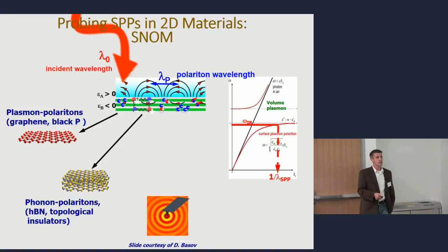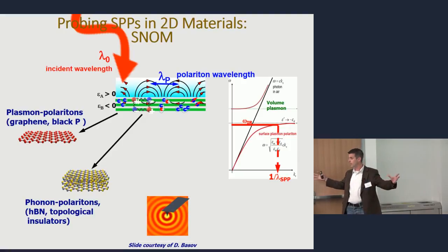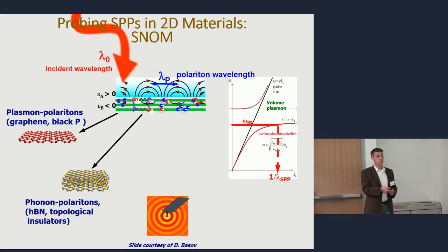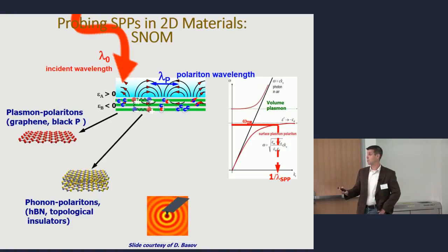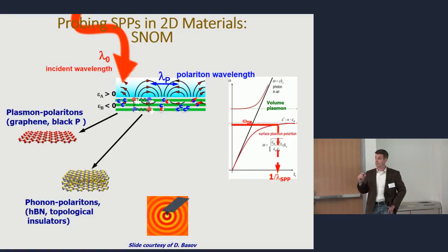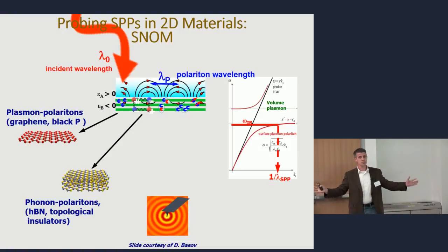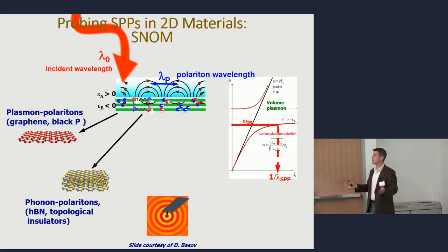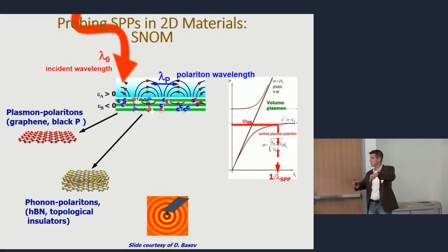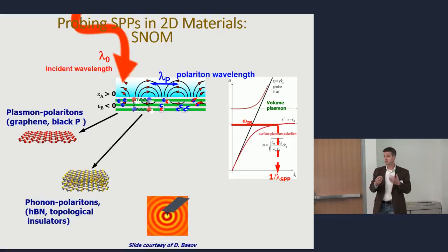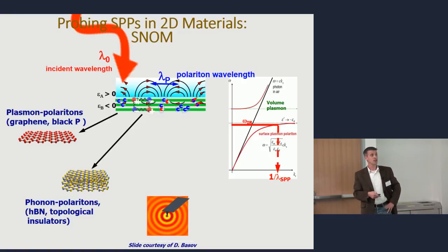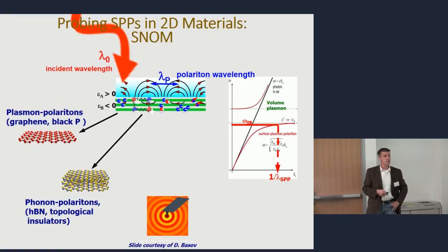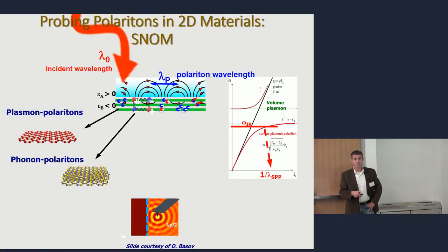All right? So this is basically like taking a rock and throwing it in a pond, and you see these ripples coming out. So ideally, you could have a metallized AFM tip. This is the basis for SNOM, or scanning near-field optical microscopy. Or I can have my light come in, scatter off this nanostructure, right, and stimulate these polaritons on the surface. Problem is, I need something that can measure that, right? So I have to have this sitting in one place, and I would need a second tip that scans. This isn't really realistic. It'd be very complex to have these two in very close proximity, considering you're talking about micron separations. So another way to get around this is to use something else.